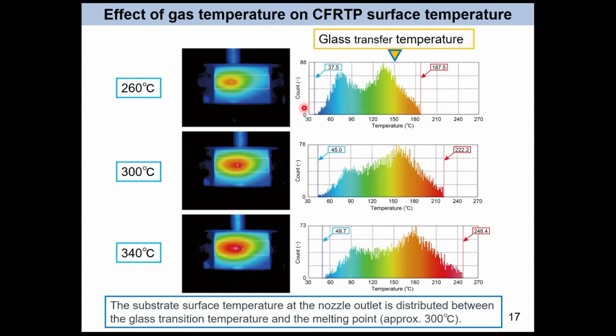When increasing the gas temperature, the maximum temperature and the higher temperature region also expanded, and the 340 case reaches up to 250. But all cases are less than the melting point. This material's melting point is about 300 degrees. So the substrate surface temperature just below the nozzle outlet is distributed between the glass transition temperature and the melting point. This thermal effect should also be effective for getting the coating on CFRP.